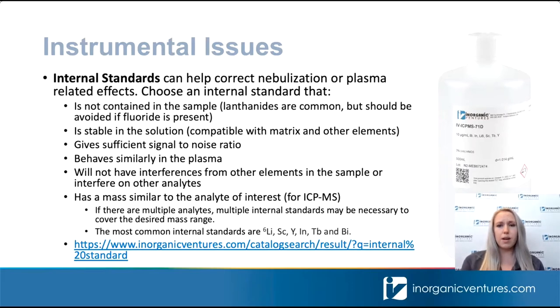But one thing to keep in mind with these is that if you do have HF or fluoride in your solutions, they can drop out as the insoluble fluorides. And so you want to make sure that that isn't going to cause an issue. And if so, you probably need to pick a different internal standard. Another consideration is, of course, the stability of the element in solution. So you want to make sure that it's compatible with both your matrix, your analytes, as well as any other components that are going to be contained in the solution.